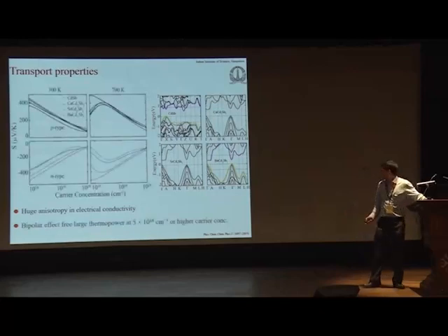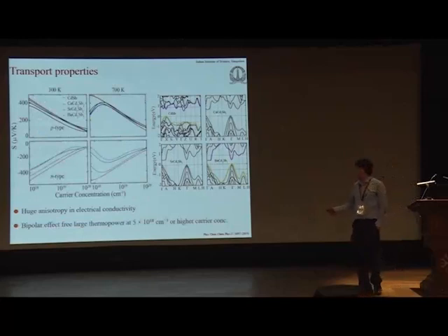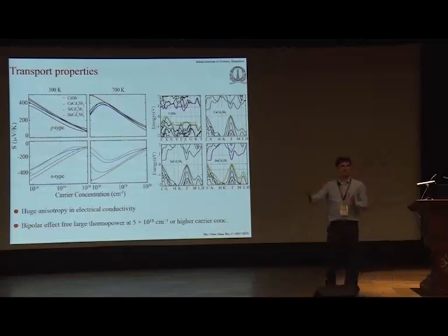That's what we wanted. And if you look at their Seebeck coefficient, for some there is a bipolar effect, where at some temperature the minority carrier also starts participating. The majority carrier has one kind of sign, and the minority carrier has another, and they start canceling. And then it leads to a peak here.